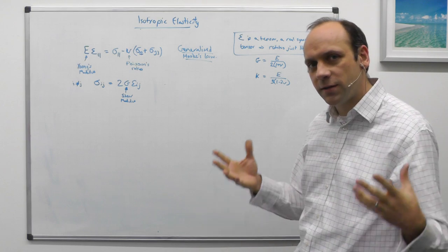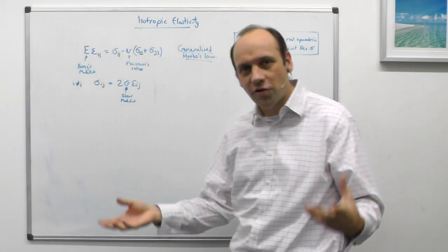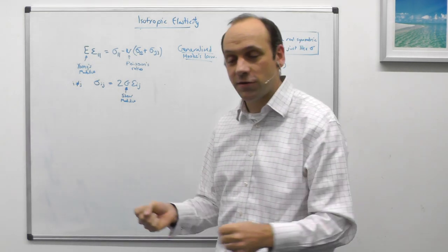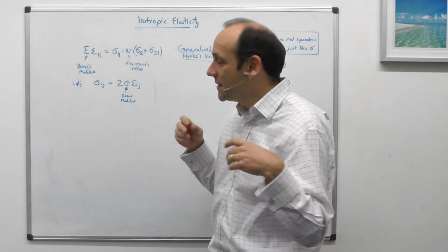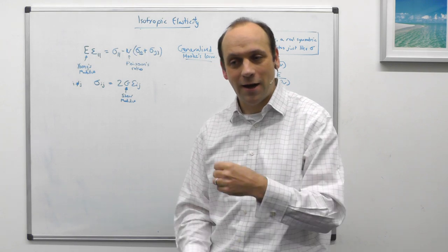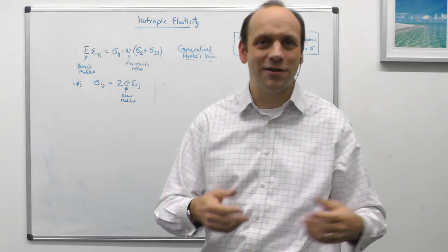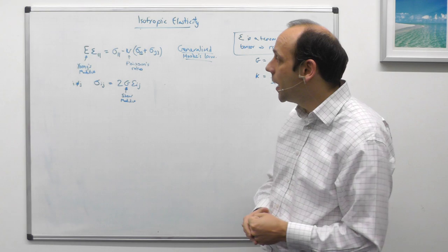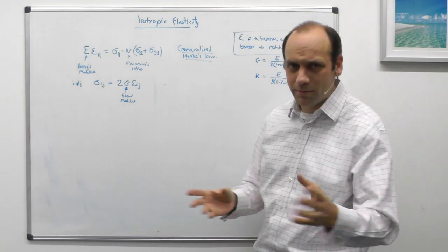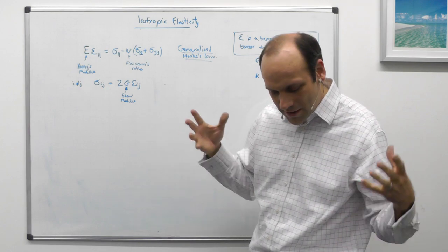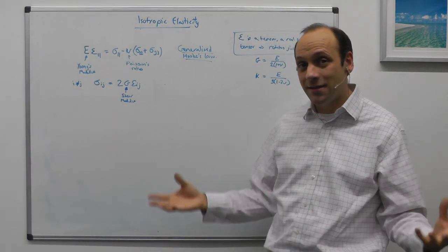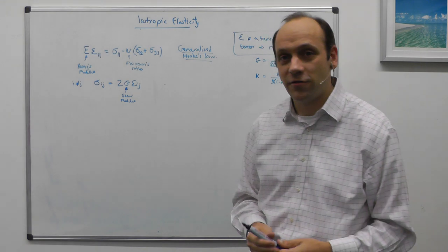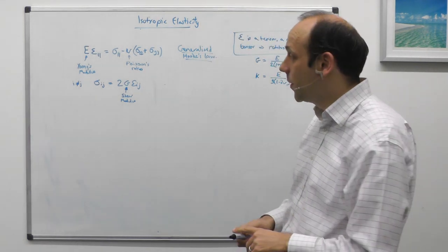And that's quite commonly going to be the case, because what happens a lot of the time is that we can measure strains. That is, we can measure how much the lattice parameters have changed, or we can measure motions of materials using a displacement gauge. But it's very difficult to measure stress itself unless you happen to have a stress measurement device, which is actually a strain measurement device that's configured. So a load cell is actually a big strain sensor, in fact. It's just a very stiff one. And in most cases, what we tend to measure in reality isn't the stress, it's the strain. And therefore, we then convert that to a stress because we want to relate it to what happens in a tensile test or to a material behavior curve.